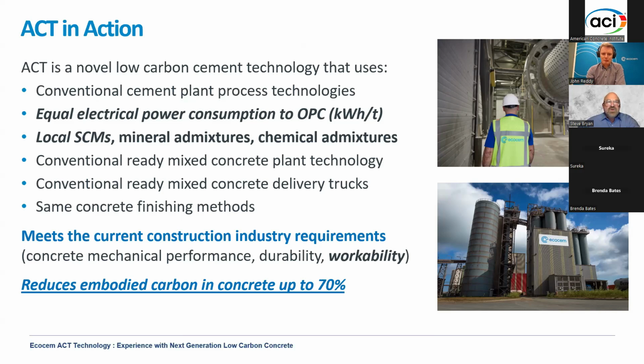We also do it with local SCMs. Our bread and butter has always been slag, but this technology is applicable to fly ash, it's applicable to natural pozzolans, it's applicable to calcined clay, you name it. And in addition, the mineral admixtures we use can run the gamut from ultrafine limestone to fly ash to any mineral, actually. It just needs to be non-reactive in that matrix. The primary consideration is the particle size itself.